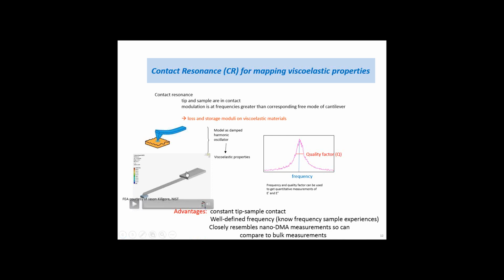But essentially, the tip and sample are in contact, and they oscillate at resonance. And so what happens is, while you're oscillating this tip-sample contact, you collect the contact resonance tune, as shown here. There are two significant parameters that we track or measure on this tune as the measurement progresses. The first is the frequency peak position, and the second is the quality factor. The quality factor, or Q, is the full width half max of the peak, or the sharpness of the peak. And so we can model this as a damped harmonic oscillator and extract the viscoelastic properties of our sample.